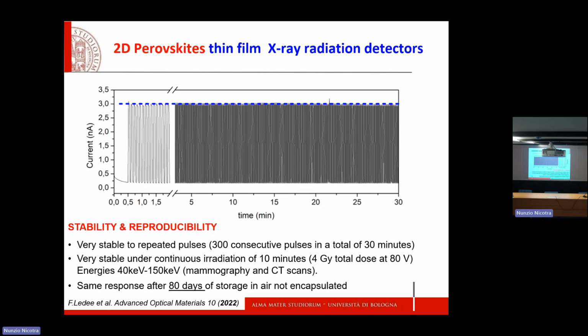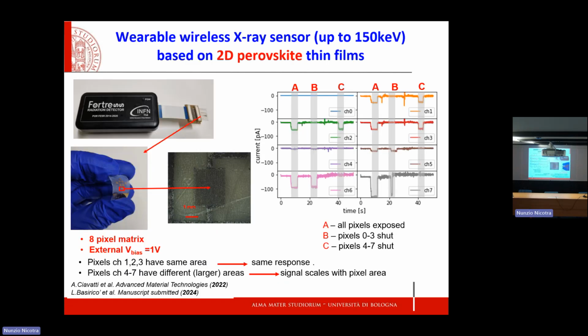Again, here you see this continuous on-off switching that is important to assess if you really want to think about applying this material. So 2D perovskites are much more stable, provide a fantastic response, and thanks to their layered and directional transport and lack of ion migration, provide very, very good performance.